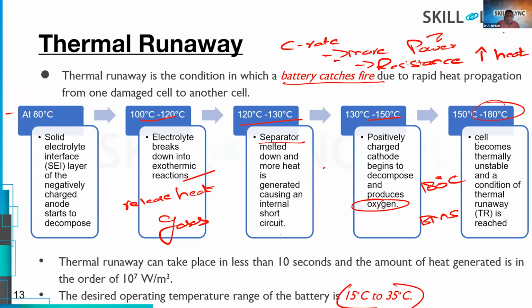Now this thermal runaway can take place within 10 seconds. Within 10 seconds, this heat propagation may start, based on the load and the battery's charging and discharging behavior. In this case, the amount of heat generated will be on the order of 10 power 7 watts per meter cube. The desired operating temperature range of the battery is 15 to 35 degrees Celsius. Even in cold climate conditions, we have to heat the battery to attain this 15 to 35 degrees Celsius.